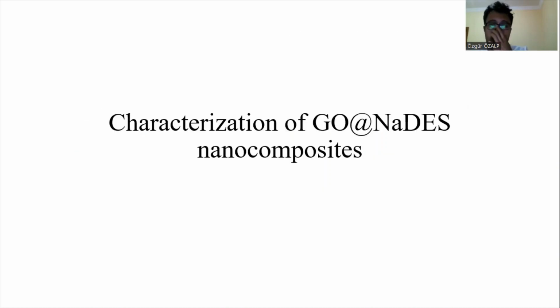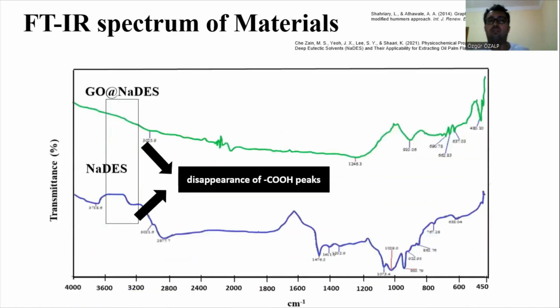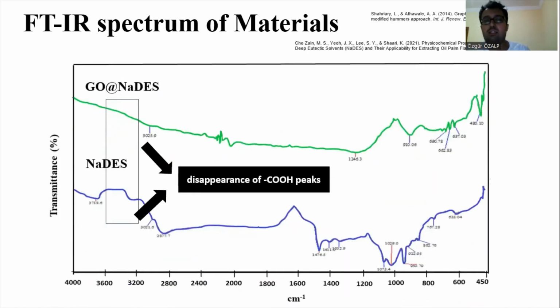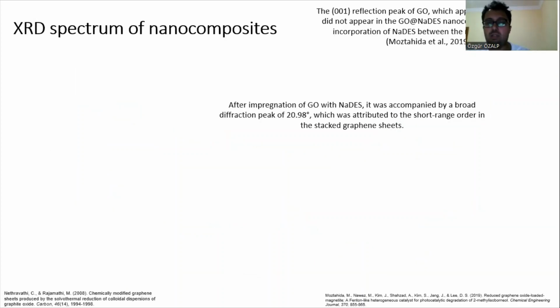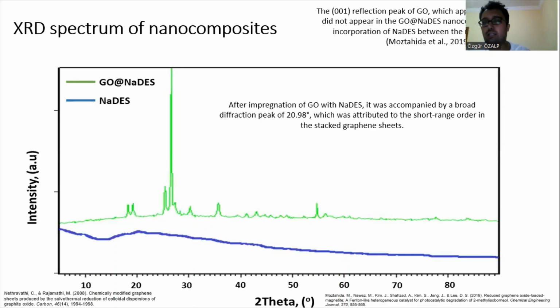Characterization of graphene oxide natural deep eutectic solvents. First of all, we use the FTIR spectrum. You can see the only difference is the disappearance of carboxylic acid peaks, released at approximately 3000 cm^-1. The second characterization is the XRD spectrum. Green is the composite, blue is the natural deep eutectic solvents. It is amorphous, and after combining, you can see different diffraction peaks.